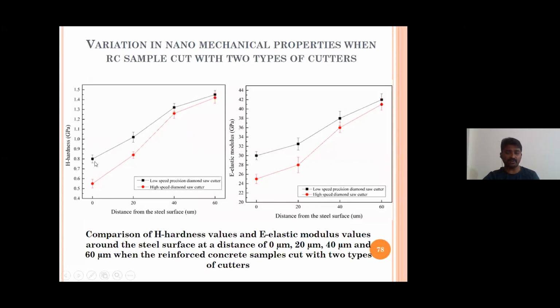At the interface, there is a lot of porosity. Because of that porosity, the hardness of concrete is less. Because of that, elastic modulus is also less. The black portion indicates the low speed diamond saw cutter, and with high speed diamond saw cutter, you are even reducing the hardness. Actually, it is nearly around 0.8 at the interface. The hardness is 0.8 and elastic modulus is 30 GPa. But if you use high speed cutters, you are directly reducing, or misinterpreting, the hardness and elastic modulus values. These values play an important role even in advanced studies. So for that we have to use a low speed diamond saw cutter.